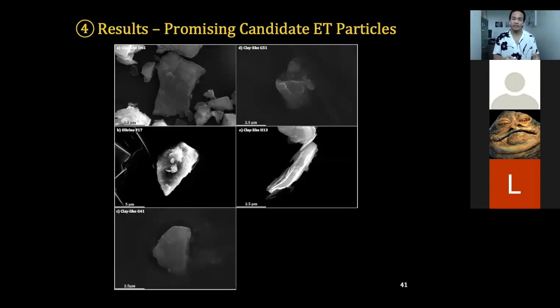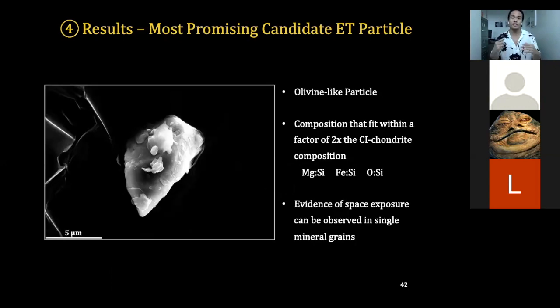We ended up choosing this olivine-like particle as our most promising candidate that we wanted to perform additional analysis on, because again, it has a composition that fits within a really strict factor of 2 times the CI chondrite composition, and that includes the full particle as well as some of the material that is on top of the surface. Again, we just looked at the magnesium to silicon, iron to silicon, and oxygen to silicon ratios. Additionally, evidence of space exposure is more easily seen in single mineral grains such as this one.